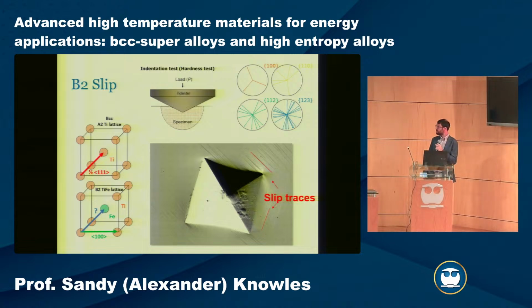Instead, with Vincent, we then were interested in the mechanical behavior of these systems. So when you deform a BCC metal, you have dislocation motion, and it's typically a 1/2<111> type Burgers vector. So you have this deformation mode where you're going from the corner atom to the center body site. And so that allows you some ability to have ductility and toughness in a material.